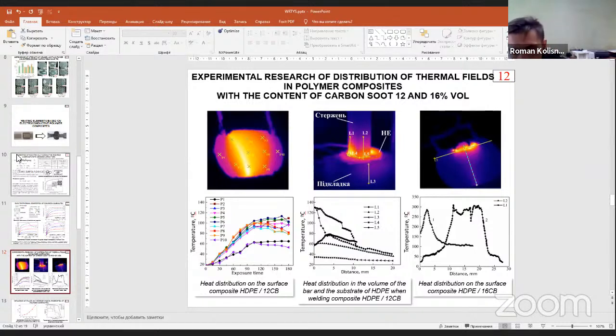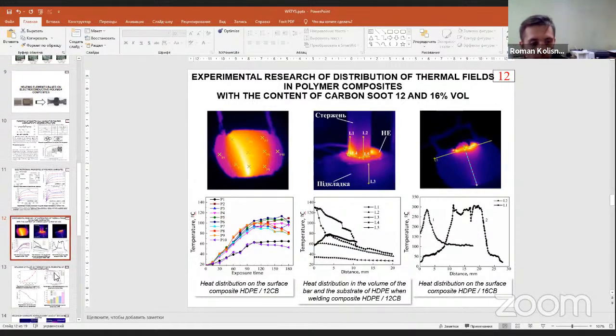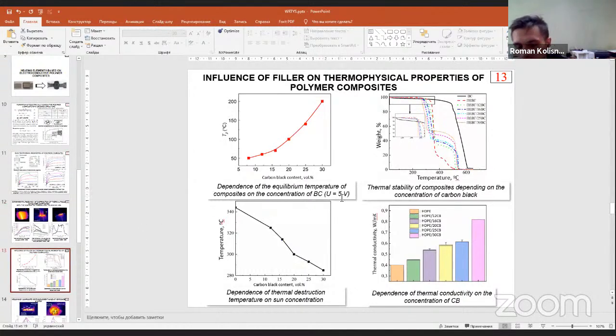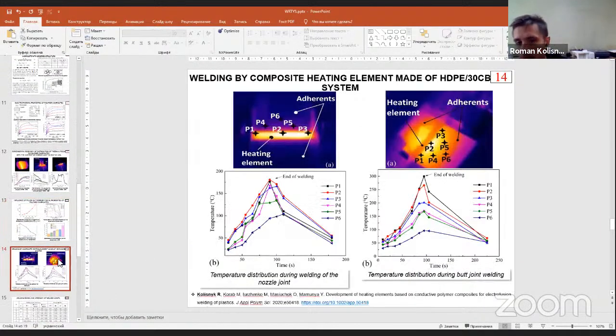So further, we increased the filler content to 30 volume percent, and in this case, after applying a value of 5 volts, the composite heats to a temperature of 200 degrees Celsius, which is much more than the melting temperature of the polyethylene. In this case, the thermal conductivity of the composites also increases, which has a positive effect on our heating elements. After that, we used these elements to weld lap joints and butt joints, and effectively used them. As you can see from the pictures, the temperature generated by this heating element is sufficient to form a weld.